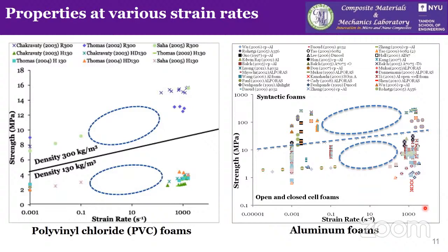So if the tests were that simple, and if you have so many different machines available, why is there this range where there's no data available? Because if the machine could go, people would have reported data. These are very common materials out there. So that became a question in our mind, and it turns out that this is a fair observation: the hydraulic machines don't go to about 100 or 500 per second, whereas the Hopkinson bar is not able to come down to about 100 per second. And there is this range which is not covered by any of these equipment.